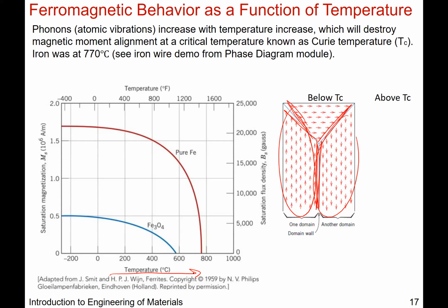And we've seen that with the iron wire demo, where Janet was increasing the temperature in that demonstration, at 770 degrees C for iron, you saw that the magnet dropped from the wire. So it lost its magnetism, and we called that the Curie temperature. That's a critical temperature below which you'll have alignment, magnetic ordering, and then you lose the magnetic ordering. And so that's captured here in this plot where you have saturation magnetism as a function of temperature.